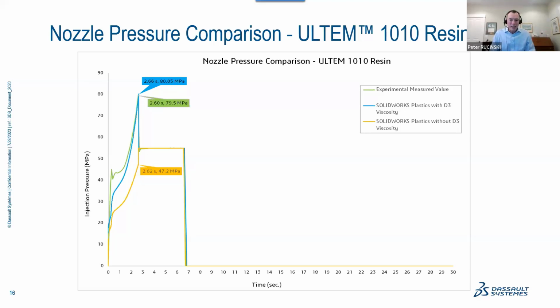And so when we first did this, SABIC said, okay, very nice job, but we gave you a problem of 2 plus 2, but the answer we got was 3. And what I mean by that is, as you can see here, we were under predicting the peak injection pressure by somewhere in the range of 25% or so. It turns out that, as Aditi mentioned regarding material data, especially for these pressure-dependent viscosity materials, oftentimes the D3 viscosity parameter is simply not there. It's not tested for or provided, or even if it is there, the injection molding simulation software may assume something different. Now, I'll admit, in our case, we had the D3 parameter programmed into our software, but let's say there was a switch which was off; we were just always assuming that D3 was 0.